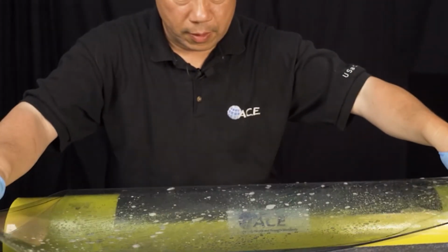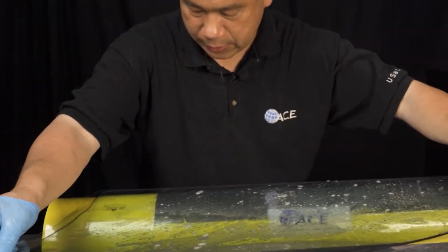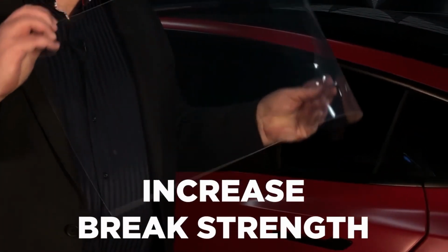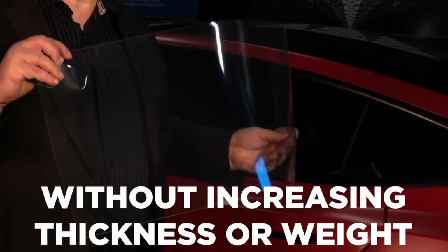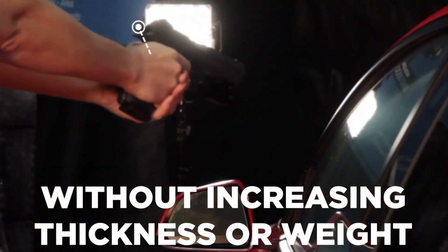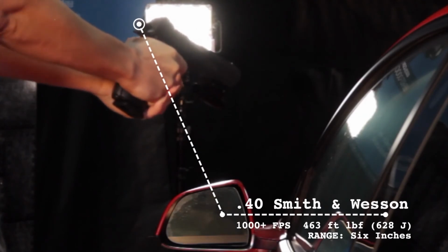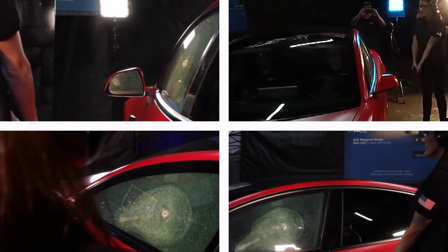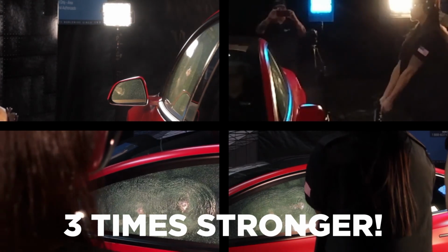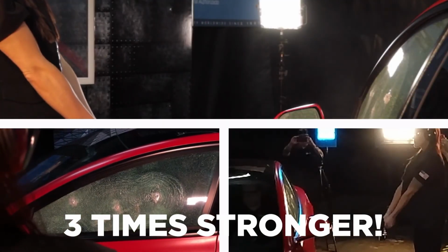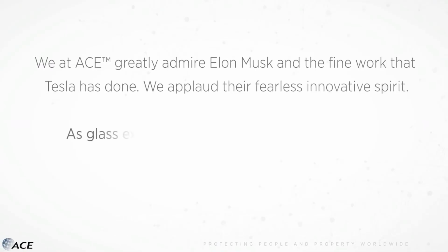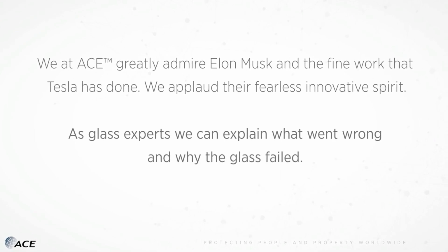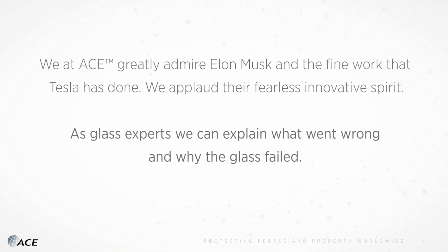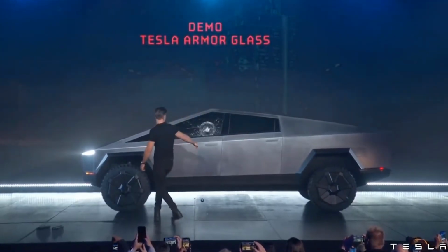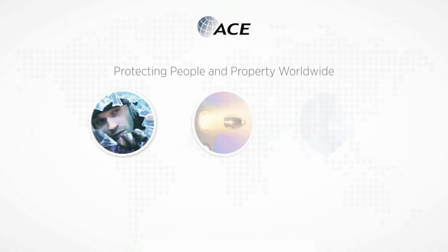So by adding a thin substrate or polymerized coating to the tension side of the glass, we can actually increase the break strength of the glass in its tension mode without increasing the thickness and/or weight loading. Depending on the properties of the substrate being applied, we can increase the break strength by almost 3 times without having to change the weight and/or thickness. With almost 30 years in the glass coating and polymerization of glass, this is our analysis of why the Tesla Cybertruck windows broke and how we recommend Tesla has them strengthened.